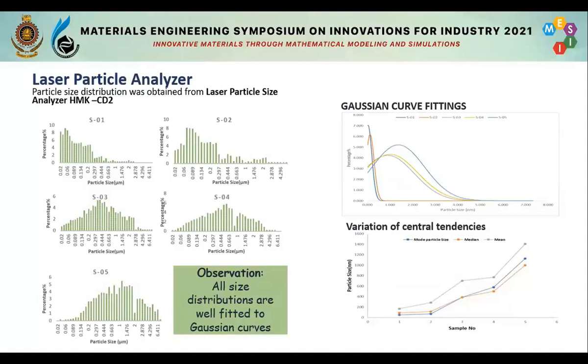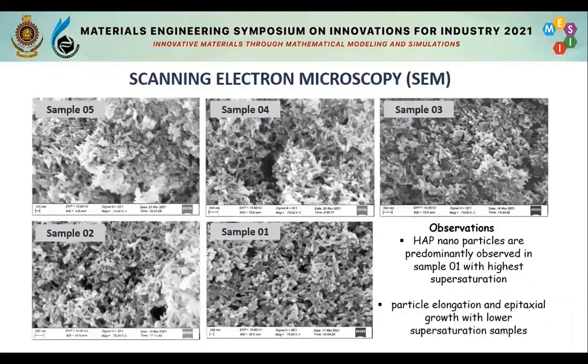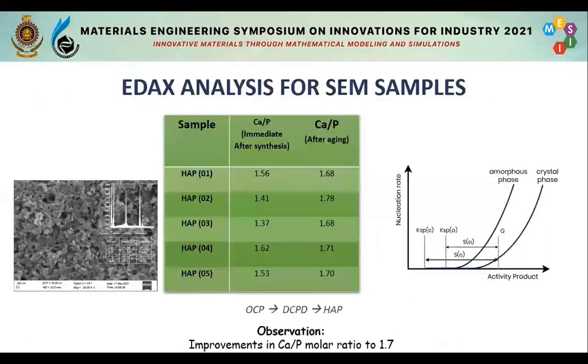Then we fitted our size distribution into Gaussian curves with highest accuracy. Then we saw the variation of central tendencies in each and every sample. As you see, the highest central tendencies are recorded for sample number 5 with the lowest supersaturation. These are scanning electron microscopy images. It is experimentally proven that sample number 5 has the largest particle size compared to sample number 1 with nano-range particle sizes. It is a kind of experimental validation for the regression model.